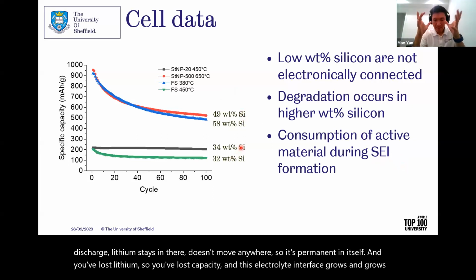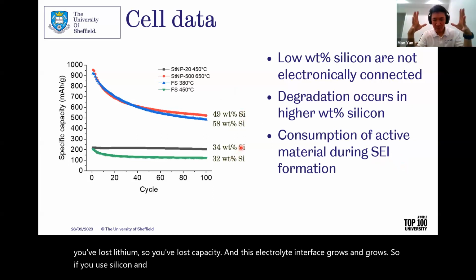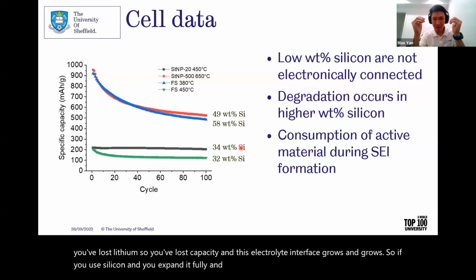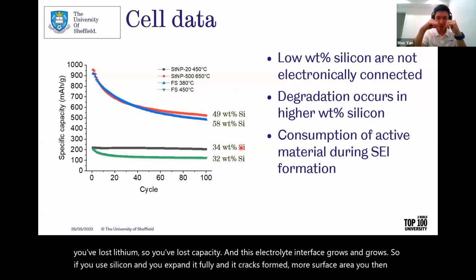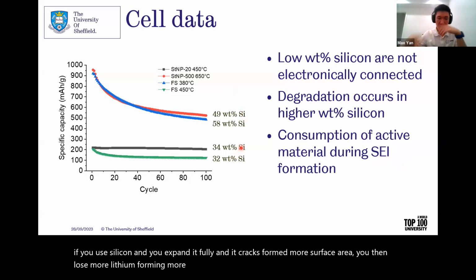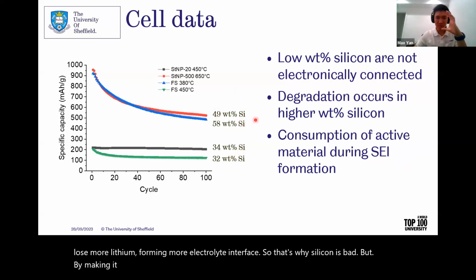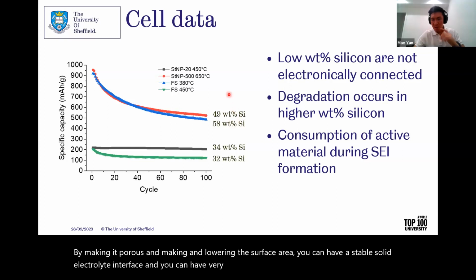So if you use silicon and you expand it fully and it cracks, it forms more surface area, you then lose more lithium, forming more electrolyte interface. So that's why silicon's bad. But by making it porous and lowering the surface area, you can have a stable solid electrolyte interface, and you can have a very stable battery from it. This is kind of all I want to talk about today.